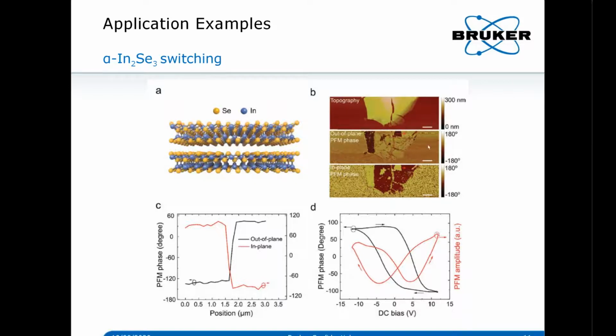But nevertheless, it's clear that you have different orientations within this flake, very likely due to the thickness of the flake. Different thickness means you have different numbers of layers underneath. So we know for sure that how many layers of these 2D materials you have definitely changes your piezo response or orientation inside. And also the alignment between these different layers affects the piezo response. So this is just a quick example about 2D materials and piezoelectric materials studies.